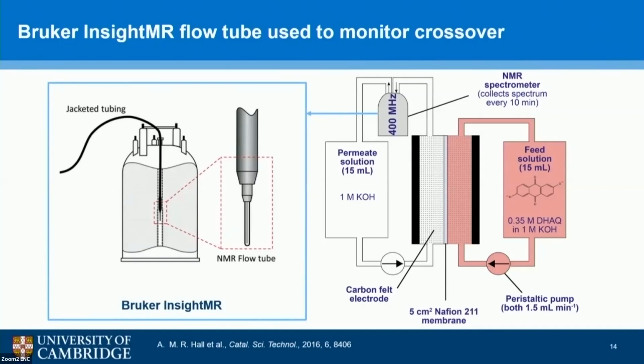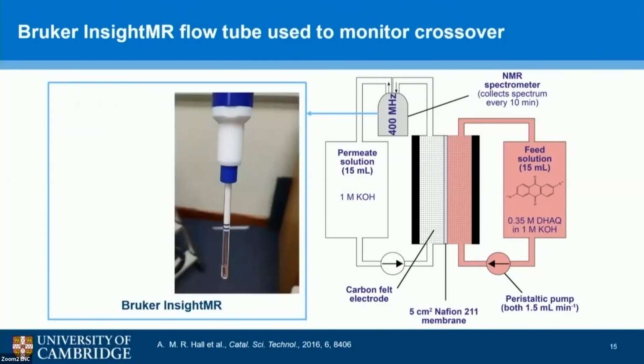The way we're doing this is using a commercial Bruker InsightMR flow tube. This is part of a collaboration with Bruker, with Matteo Pinentri, who has lent us this equipment. This is really useful because, as you can see here, it looks very similar to a normal 5 mm glass NMR tube, which means we can put this straight into a standard 5 mm NMR probe. So we can use this in pretty much any spectrometer in the department, which is great.